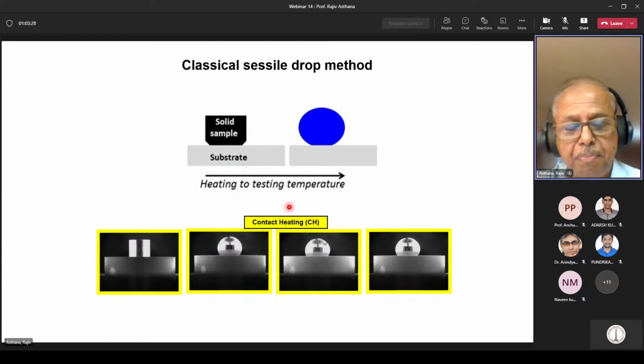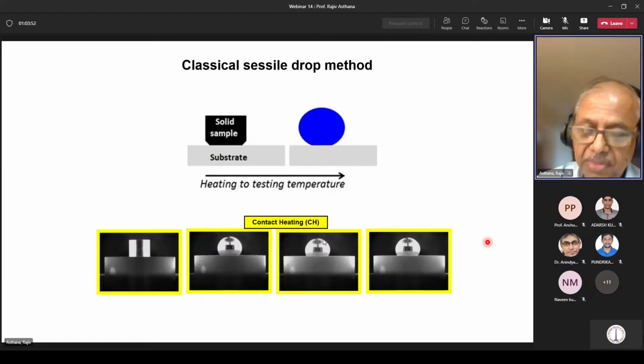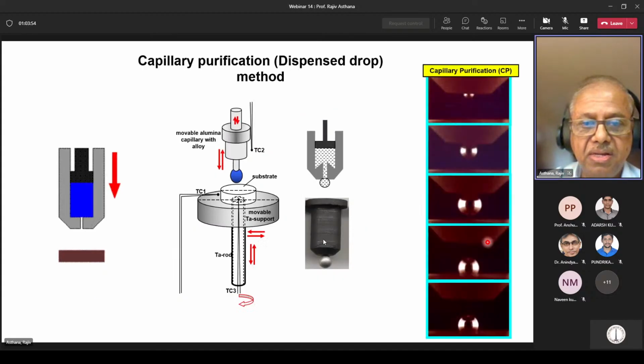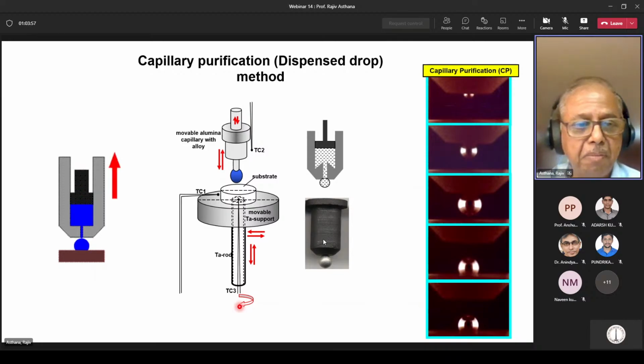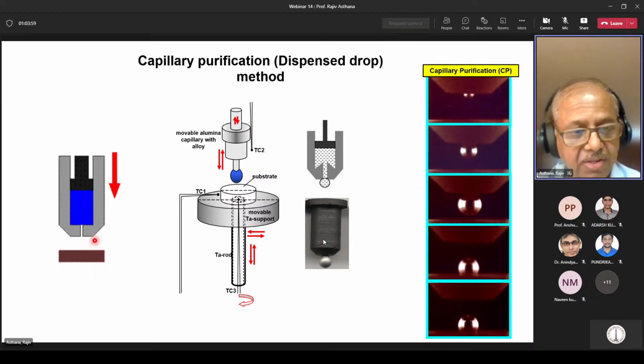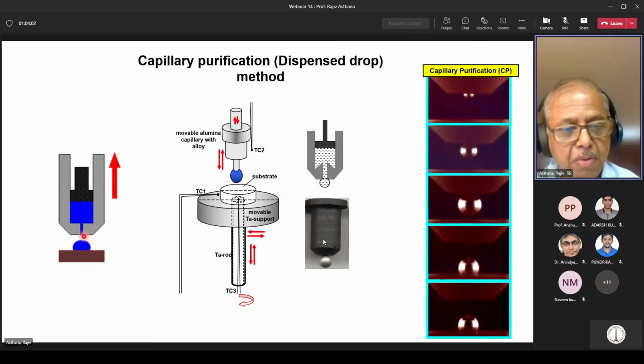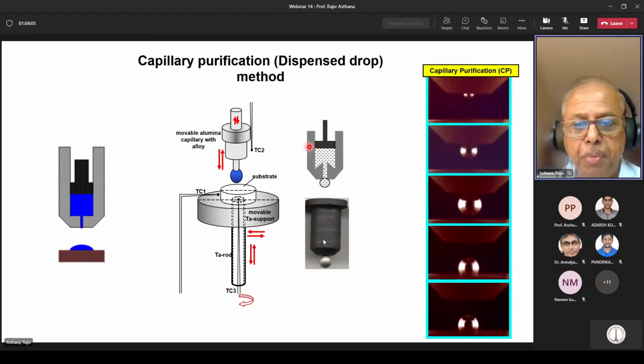The problem in this kind of experiment is that you have no way to control the reactions or interactions taking place while the solid samples are getting heated. And also, it is difficult to time the beginning time for interaction between the liquid and the solid because the melting process is not obviously instantaneous. So because of these challenges, this kind of a contact heating is not the best method. A better method is what we call capillary purification process, where you squeeze a liquid metal out of a high purity aluminum oxide capillary.